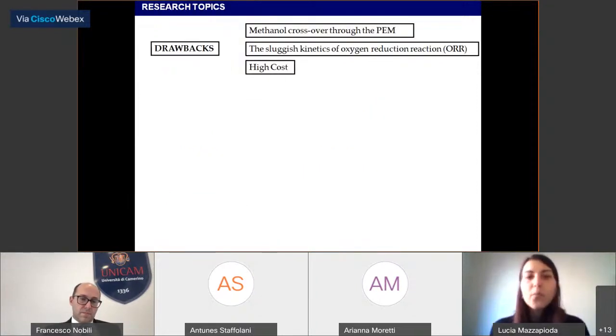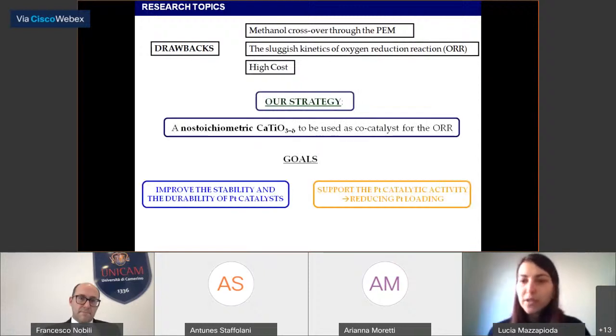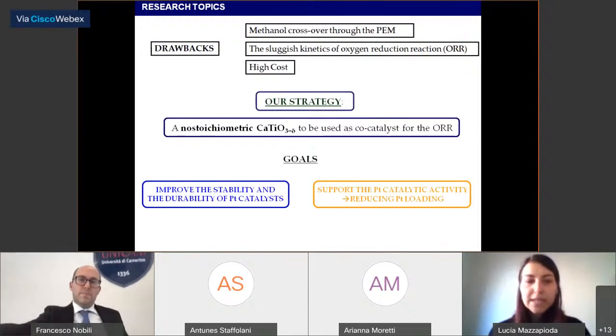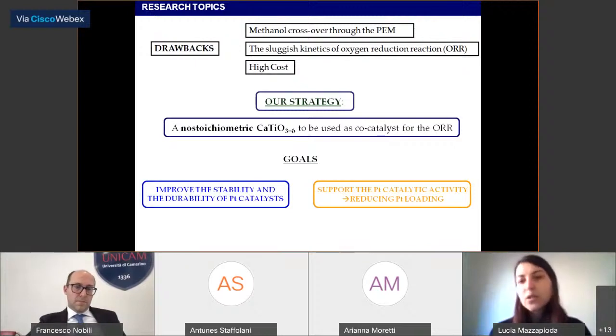However, there are some drawbacks to overcome, in particular the methanol crossover through the membrane, the sluggish kinetics of oxygen reduction reaction, and the high cost to allow the direct methanol fuel cell commercialization. A strategy to improve the efficiency of this device was to use non-stoichiometric calcium titanate perovskite as co-catalyst for the oxygen reduction reaction, with the aim to improve the stability and the durability of platinum catalyst and support the platinum catalytic activity in order to reduce its loading.